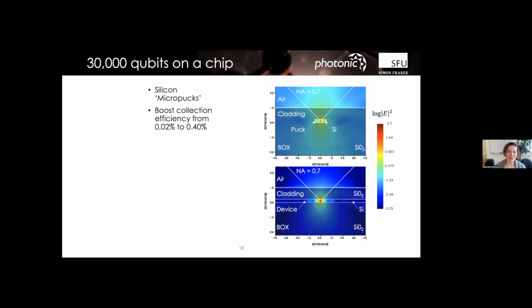And what you do when you look at other color center labs is you go and you make a cryogenic confocal microscope and you go and take a look at them. The problem with silicon is that what makes it, especially SOI, like the material that you use for integration, so good for an integrated photonics platform is that the light is a really high index, right? It's like 3.4. And so it really keeps the light inside that device layer. The losses aren't really high, which means if you're going to go take a look, it's really hard. And these things are already pretty long lived from an optical lifetime perspective.